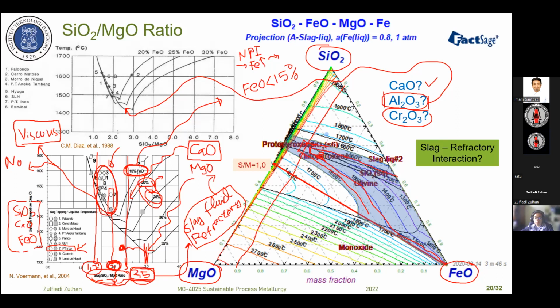And then adjust the silica to magnesia ratio in order to get into this area. In this case, if you look at the SiO2 to MgO ratio 1.5, this line is still not inside the liquid area, and then 2.3 is too high, and then 1.8 is right. This is the reason why people adjust the silica to magnesia ratio for the actual plant to around 1.8, in order to get to this point, this area. This graph is also similar to this diagram here.